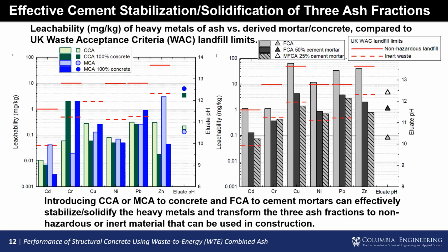As we can see from the concrete result, in all concretes the leachability of heavy metals was reduced to less than the inert waste limits, except for chromium, because the Portland cement has a higher concentration of chromium than the ash. And this is the story of the fine fractions. As for the fine combined ash, cadmium, copper, nickel, and lead exceeded the non-hazardous landfill limits.